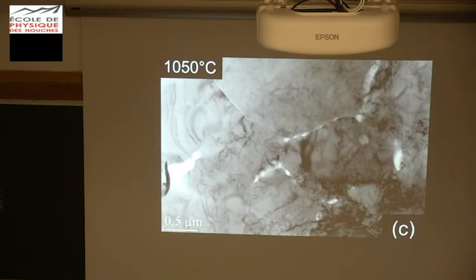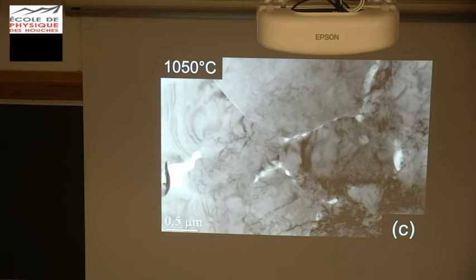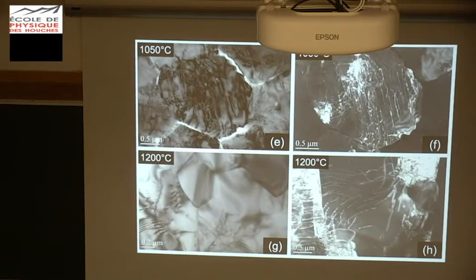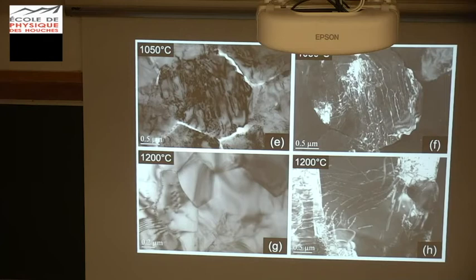One of the most extreme gap formations in the samples shows those decohesion cells — also called crocodile teeth, as this project named them for a long time. It looks something ductile, even if the outcome is something brittle. After seeing the most dramatic effect, we started to look for the initiation of this mechanism. You have a cracked grain boundary and a grain moving, with cells opening along the grain boundaries. If you increase temperature, you can also find big grains with crocodile teeth or decohesion cells on the borders, and they're still full of dislocations. It's not a single mechanism — geologists like to simplify deformation to one mechanism, but here is an example of how they can coexist.